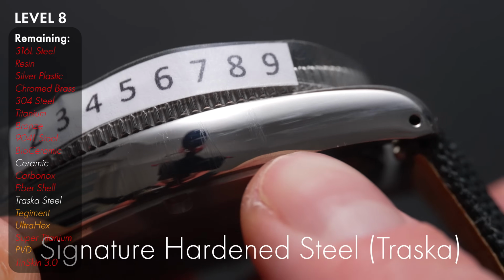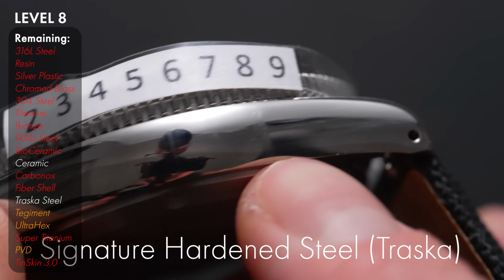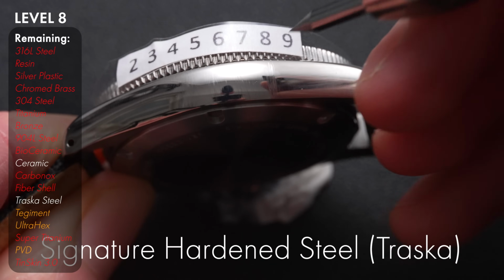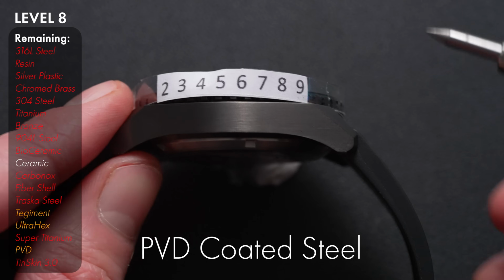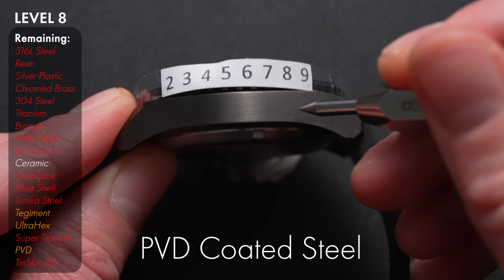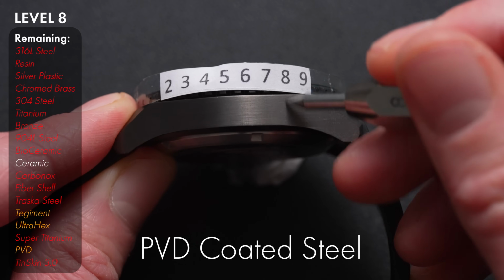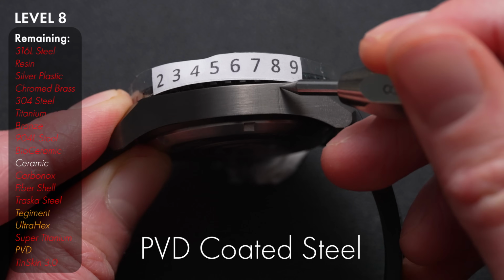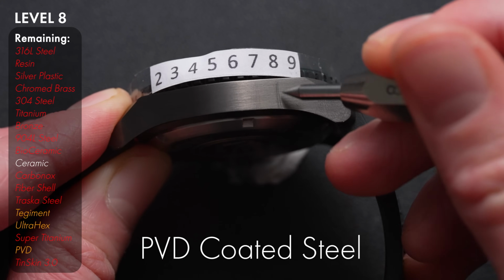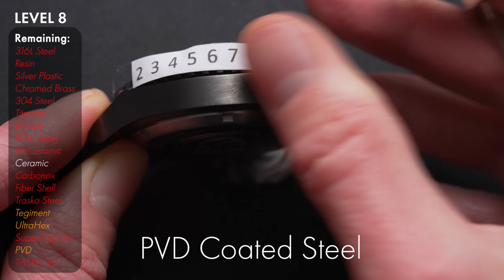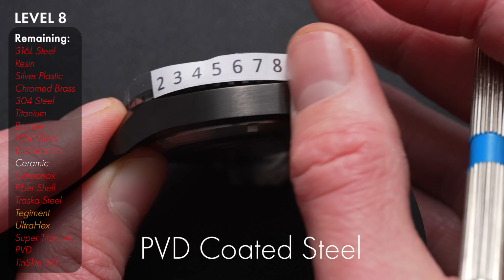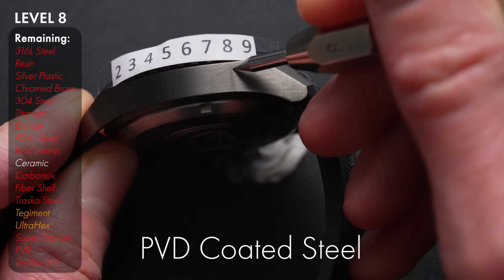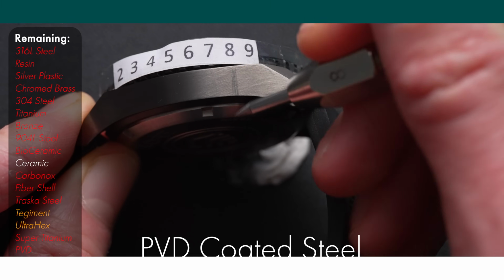In retrospect though, after comparing the footage and the watches side by side, the scratches were more obvious than those last two. So unfortunately, it receives a retroactive elimination. The Traska still edged out the PVD watch, which scratched slightly more easily at level 8. So PVD is definitely starting to scratch more noticeably this time around. That's gonna have to be the end of the PVD's road there. That's definitely deeper than all the others we've had so far at level 8.